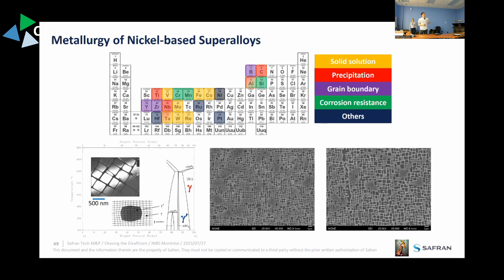As I showed you in the introduction, there are lots of elements, each of which has its own role, either on solid solution strengthening or precipitation strengthening and grain boundary strengthening. Then you have environmental resistance. The idea is that you have to play with a lot of elements. Nickel is a very accepting element, so it makes things harder. But what you're looking for basically is in this phase diagram, this is the aluminum-nickel phase diagram. You're looking to have a gamma matrix with gamma prime Ni3(Al,Ti), etc., precipitates, which you can see the distribution that we're aiming at for these alloys, with cuboidal gamma prime surrounded by channels of gamma. And this is a microstructure very resistant to creep, to dislocation progression.